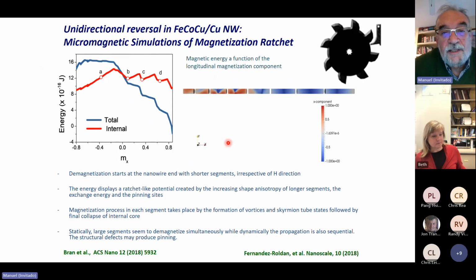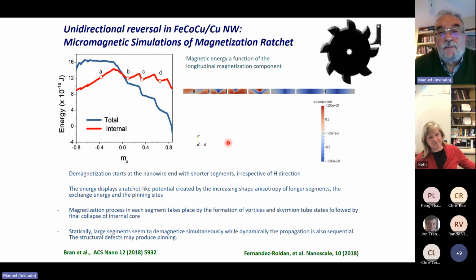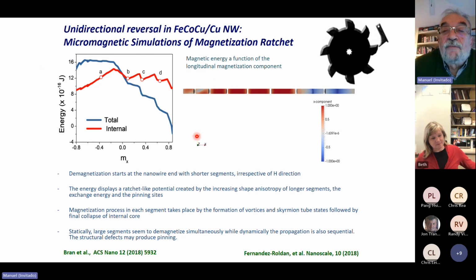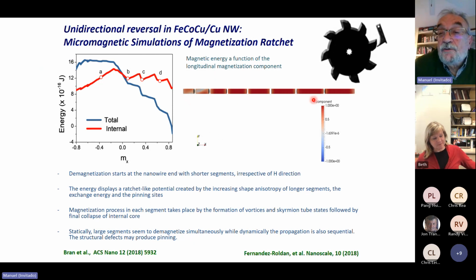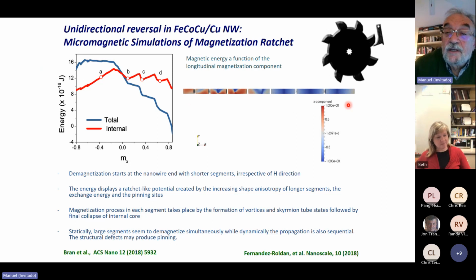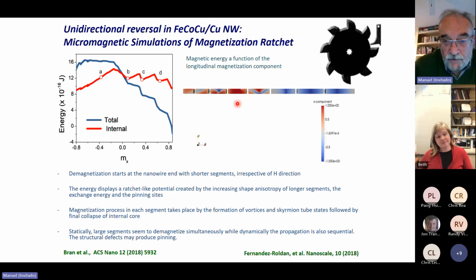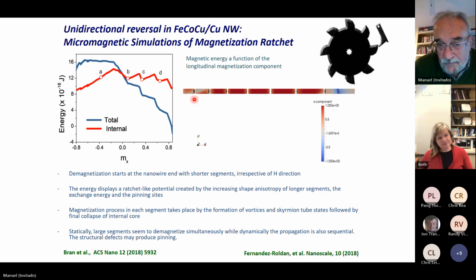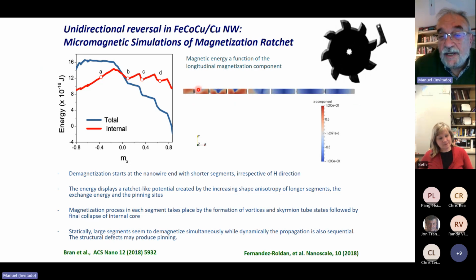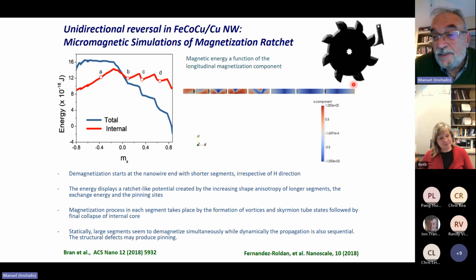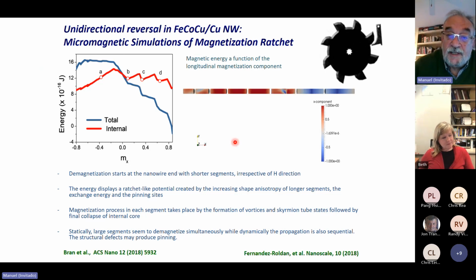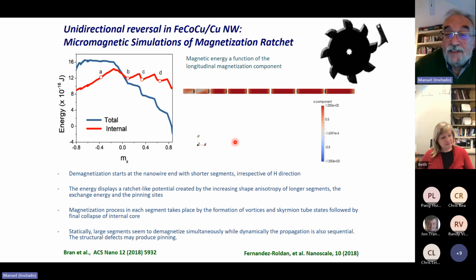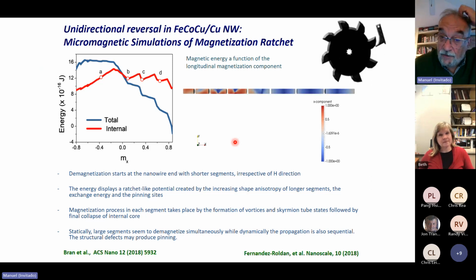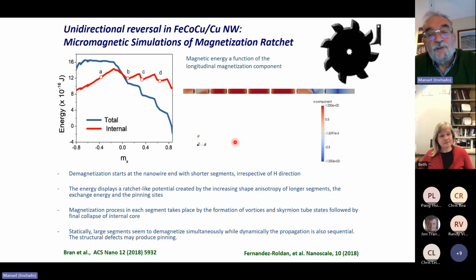The micromagnetic analysis of this magnetization reversal process has been performed. This is a video schematic. You see the schematic signal of the different segments. So the reversal starts near one end and propagates toward the right. This is what we call magnetization ratchet, because magnetization reverses from the same end unidirectionally, independently of the direction of the applied field.